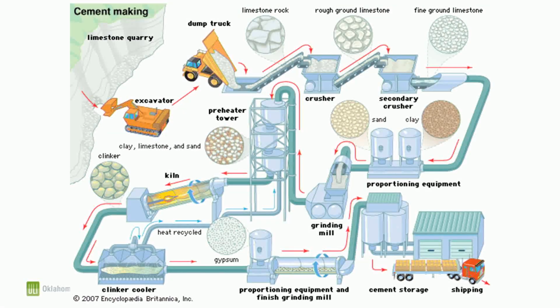There's a very important piece of the process where we quench the material by cooling it down very quickly, and that keeps those cementitious properties in the clinker. Clinker is the final product from that kiln. You're going to see it in a second. We mix it with gypsum to control set time, and we ship it to the ready-mix plant or to the sacking facility where we bag it, okay?